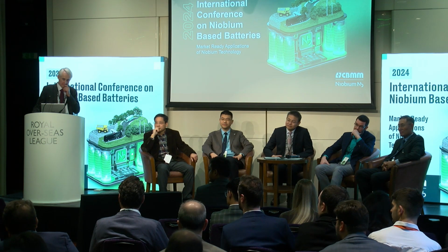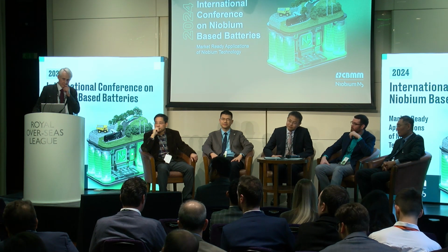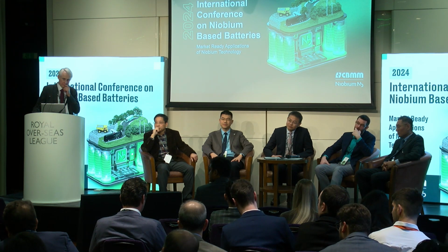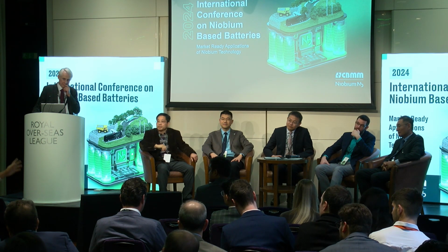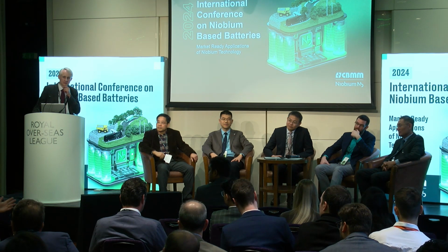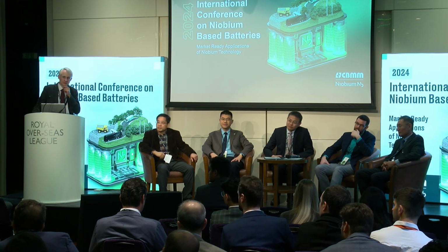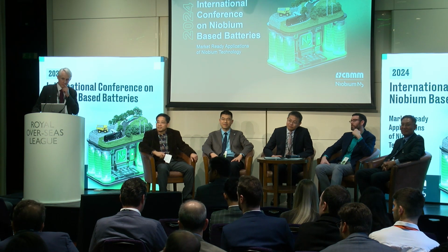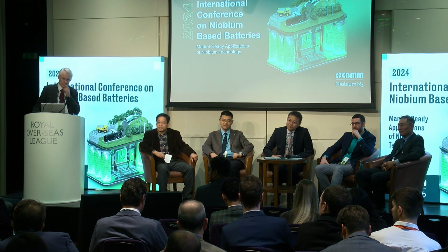And in this addressable market, depending on the formulation, we are working in the range of 0.3% niobium addition up to 0.7, 0.8% niobium addition is the necessary amount of niobium. More than that, as we could see here, we can have even bad effects. So that is not necessary, okay? But it's pretty much a drop-in solution in terms of cathode. For anode, we are going to see in the afternoon is a little bit different, but for cathode, that is pretty much the expectation.